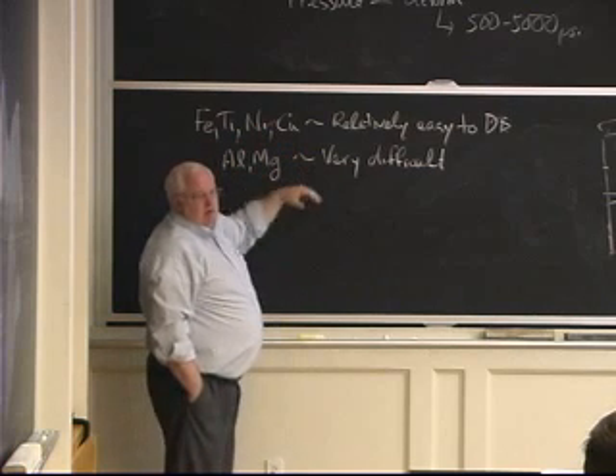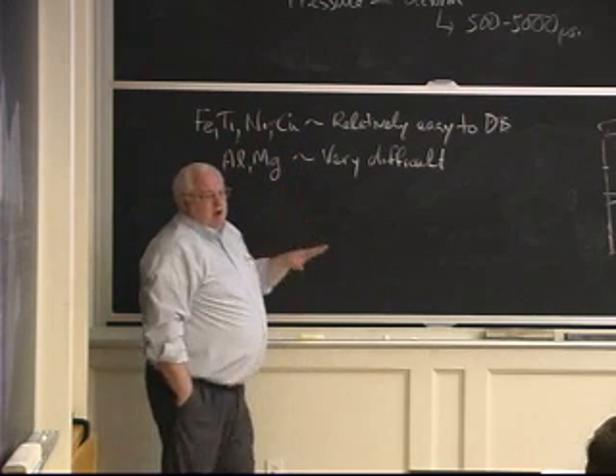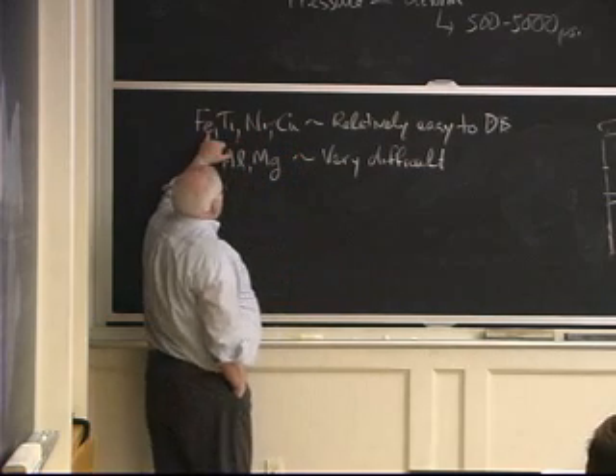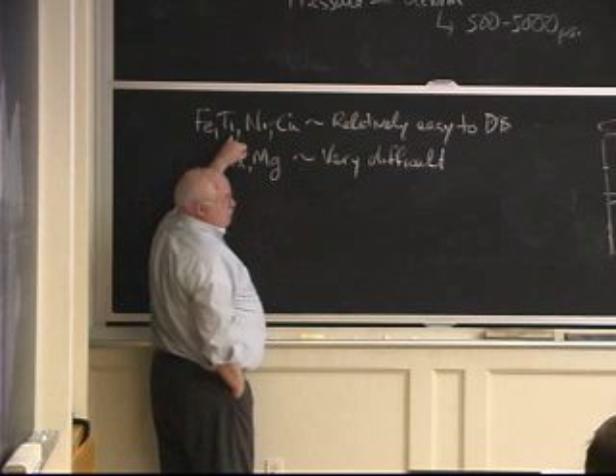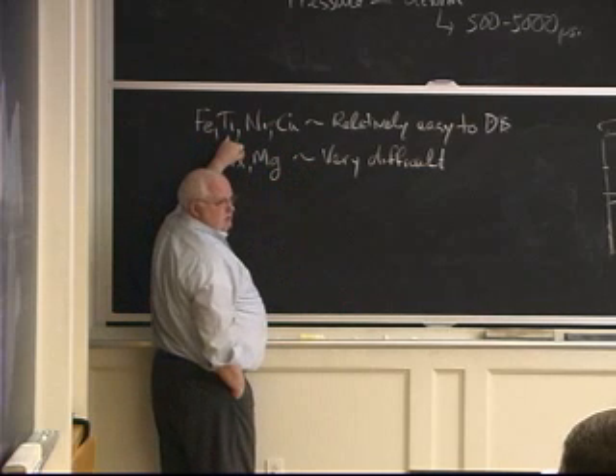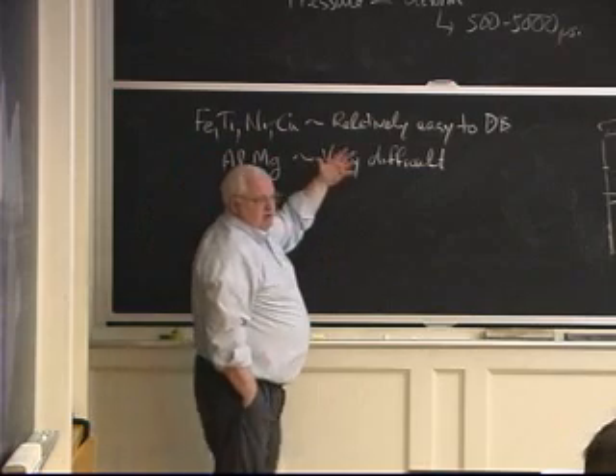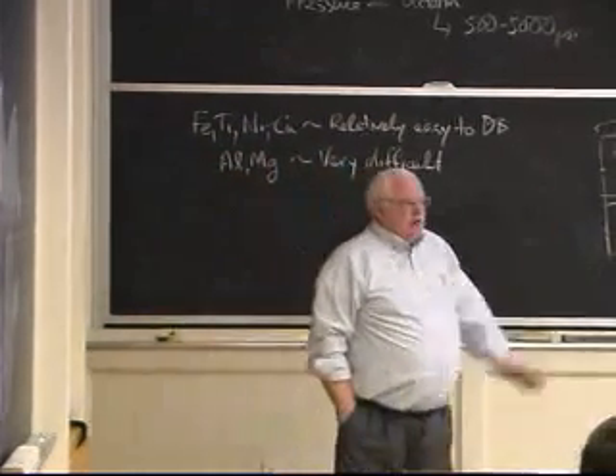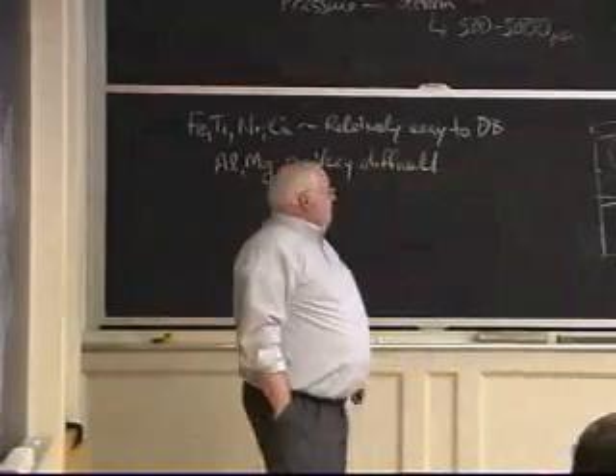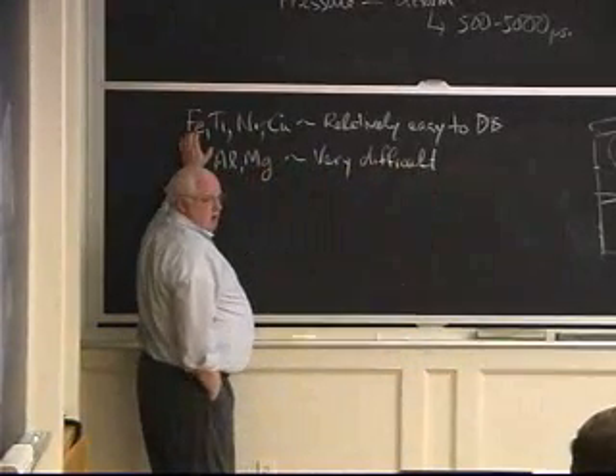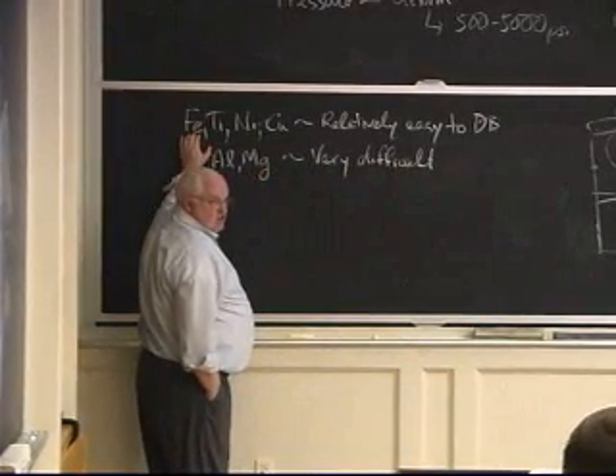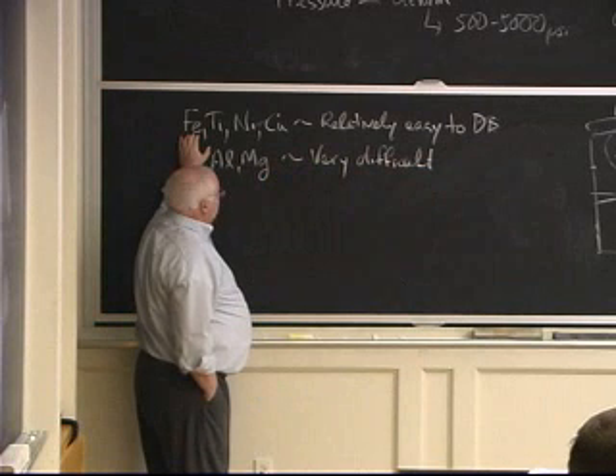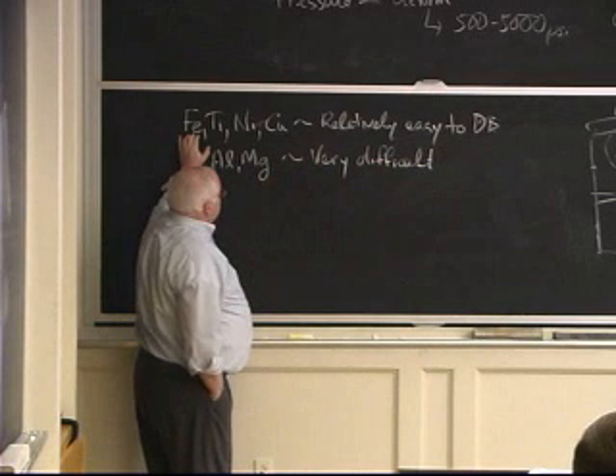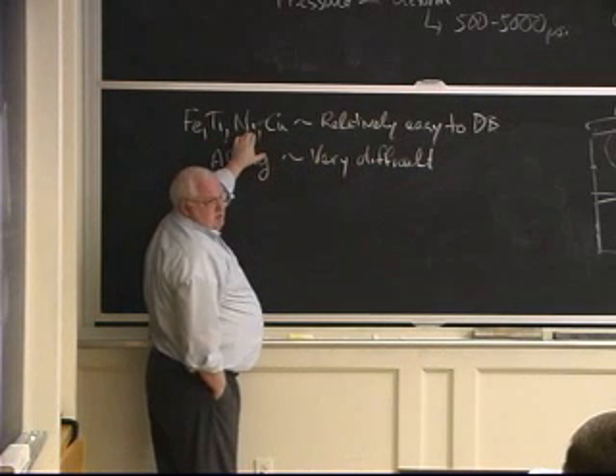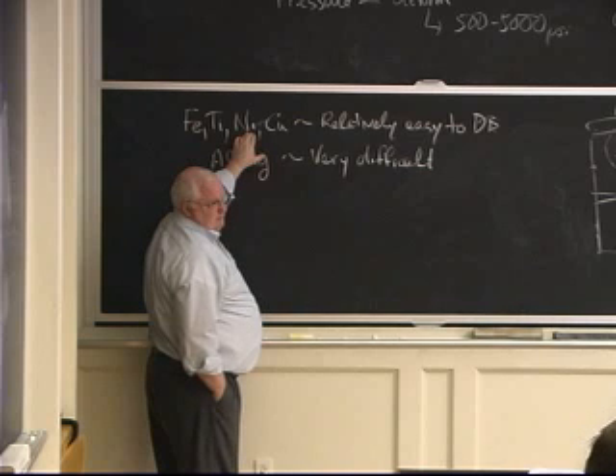But they're all relatively easy because they will diffuse away contaminants. Iron will also diffuse carbon, so will titanium. Titanium will diffuse away almost anything: carbon, nitrogen, oxygen, any type of contaminant you can think of on the surface. Hydrogen, titanium loves it. Iron will diffuse away all those things. Carbon, if I have CO2 or CO on the surface, it'll diffuse into the base material. Nickel doesn't diffuse carbon.